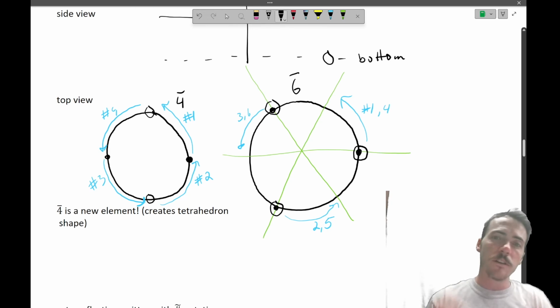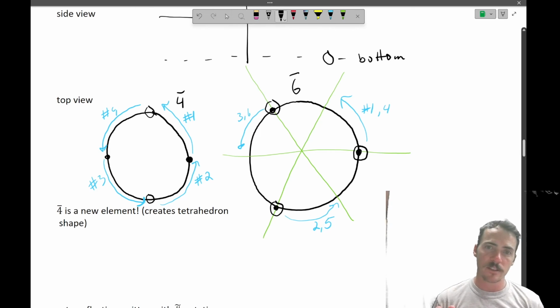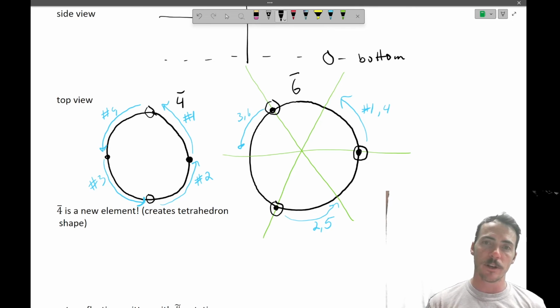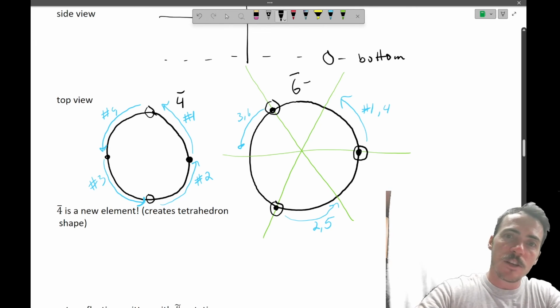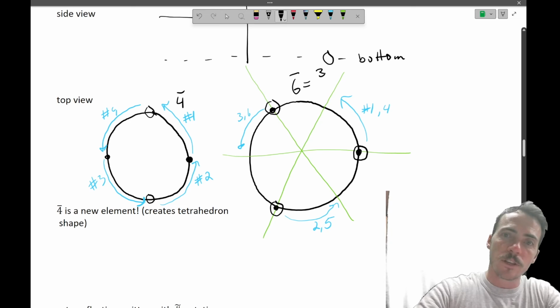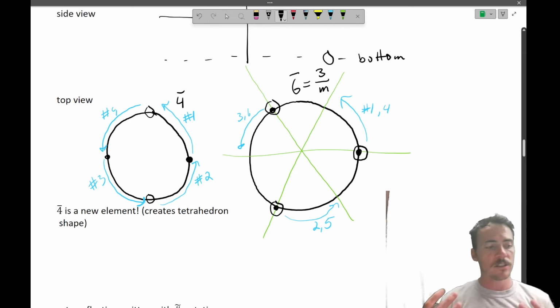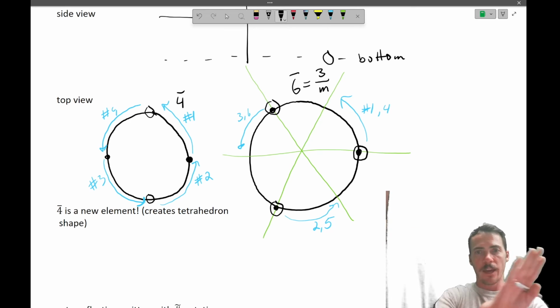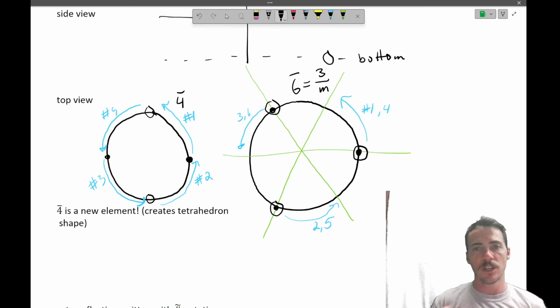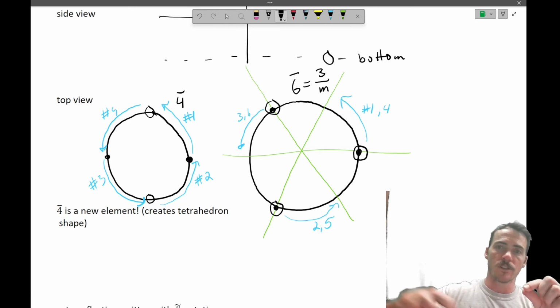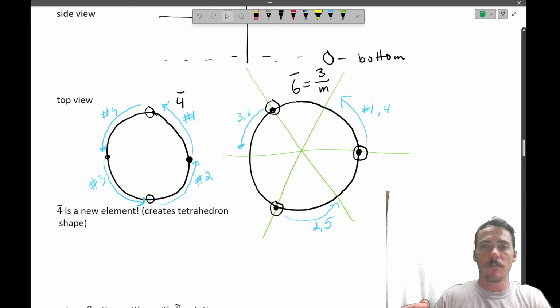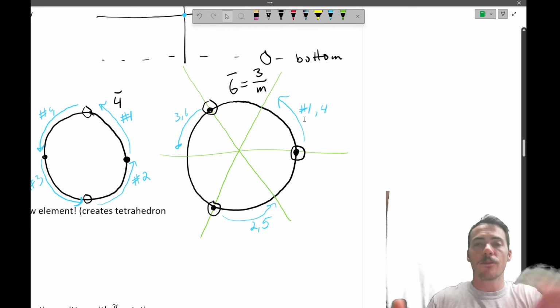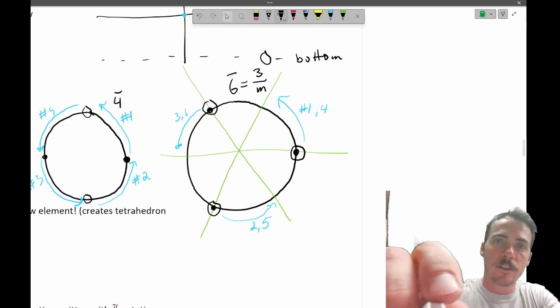And if you look close, you could imagine that this is actually equal to several other symmetry elements combined. This is equal to a 3-fold rotation and a mirror symmetry, right? So this one symmetry operator is actually composed of two other ones. Like if there was a mirror plane in the sheet of the image here, there's atoms above and below that symmetrically, and there's threefold rotation, right? Same. So this produced the same thing, right? And then if we look at threefold roto-inversion, it would look like this.